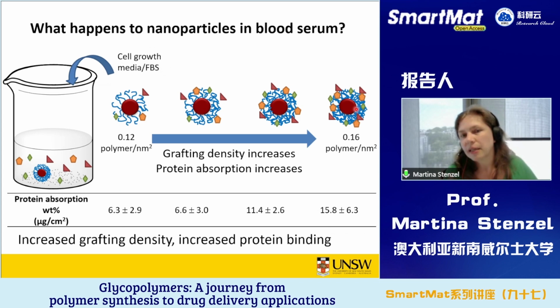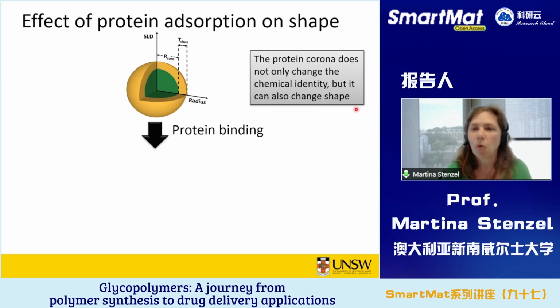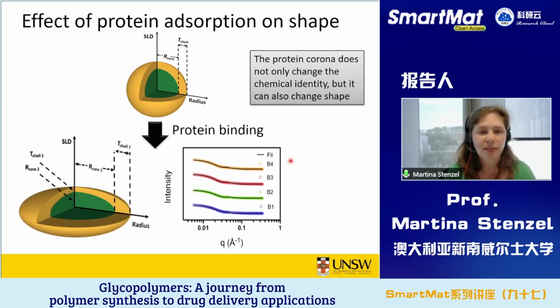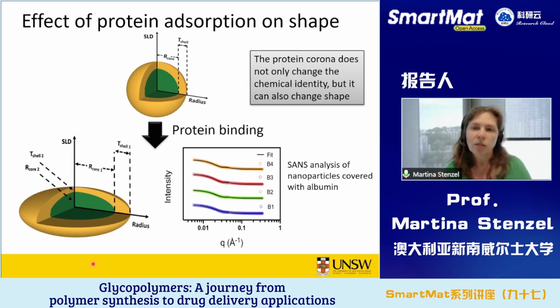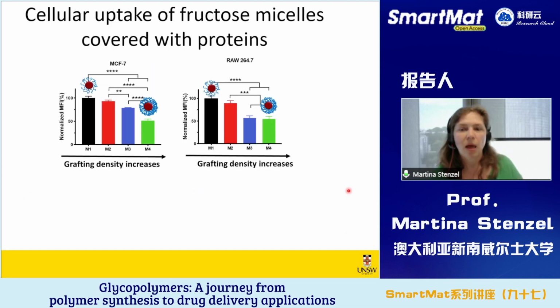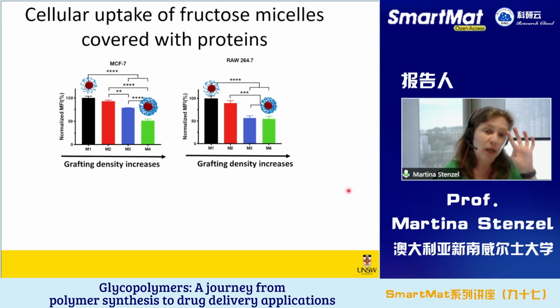But then we went back and said, well, let's explore the nanoparticles after they've been in serum a little bit more, and learn more about the shape of these nanoparticles. We started off with these core shell micelles. The yellow part here is the glycopolymer, and we incubated now with protein. And we did X-ray scattering again. What we found was that the protein had the power to deform these nanoparticles. Out of a round particle, we got particles that were almost spheroid in structure. With SAXS and SANS analysis, we found not only is it covered with albumin, but also the particles are deformed. And this very much influenced the biological outcomes.